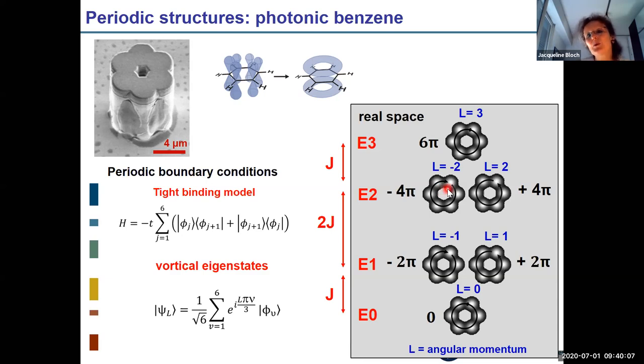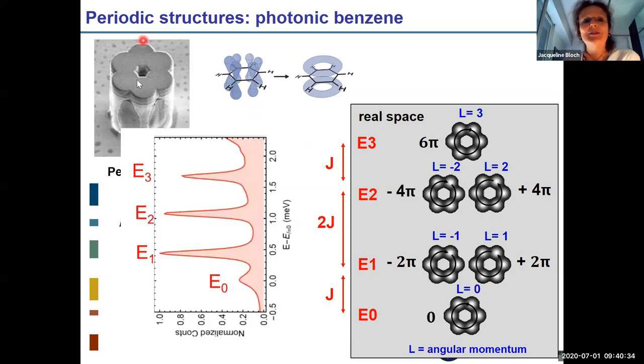And actually, this corresponds to modes which carry an orbital angular momentum, L equal plus or minus h bar, or L equal plus or minus two h bar. It means that the phase is winding as you go around the molecule, you get a phase accumulation of plus or minus two pi, or plus or minus four pi. So when you look at the spectroscopy, you excite such a molecule and you look at its photoluminescence, you indeed see these four levels.